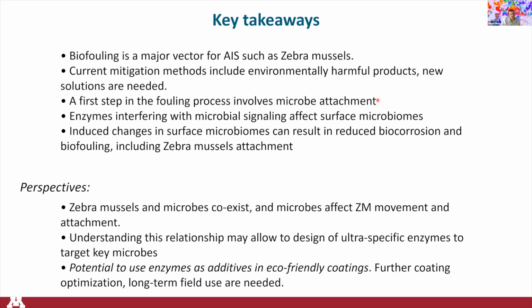So the key takeaways from this is that biofouling is a major vector for aquatic invasive species. The current mitigation methods are not great, and some of them are very toxic to the environment. And in this process of biofouling, microbes are extremely important. We have enzymes that can interfere with microbial behaviors, and these enzymes change the surface microbiome, and that change in the surface microbiome, we believe, is responsible for the change in biocorrosion and biofouling that we observe. And some of the perspectives of that work is that zebra mussels and microbes coexist, and somehow they seem to have a very interesting relationship where they probably influence each other.